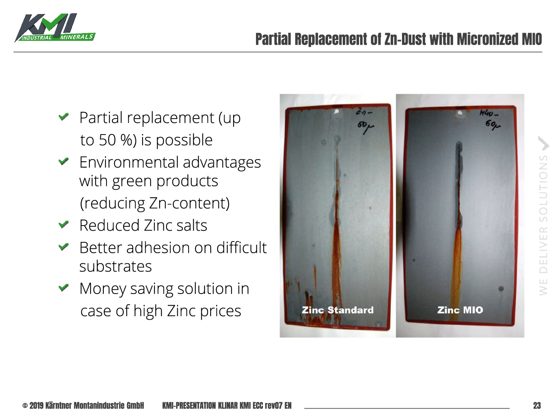The latest results we have on this application is that a replacement rate of up to 50% is possible to get similar performance, but we also found out that at loading levels of around 10% you can really improve the performance of an existing prime coat.